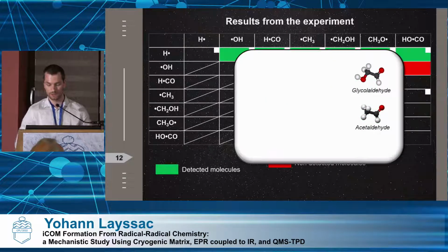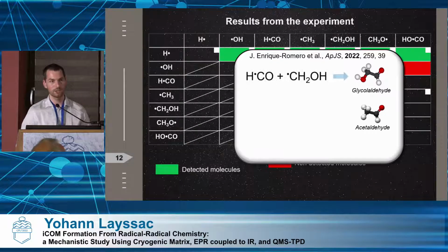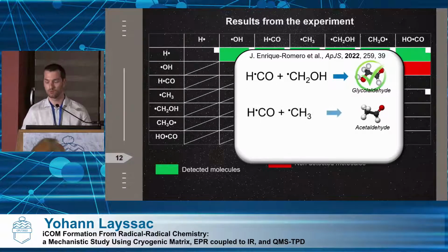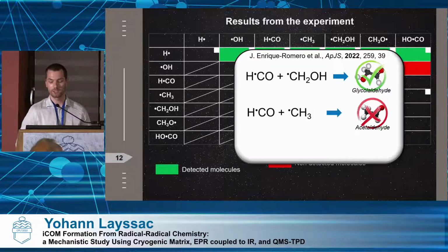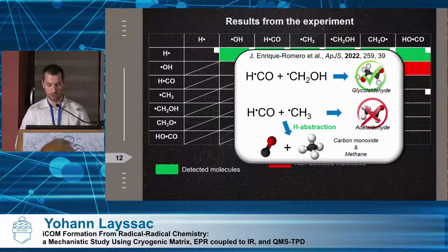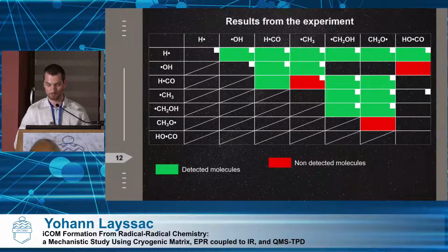So we can take this theoretical work done by Enrique Romero, when he showed that in a cluster of water, the HCO plus CH2OH is effectively working to give glycolaldehyde, but HCO plus CH3 does not work and does not lead to acetaldehyde, because there is another reaction pathway that is highly preferred, that is the H abstraction of HCO to give CO and methane. So that's probably what we obtained also in our experiment for all these 3 red molecules.